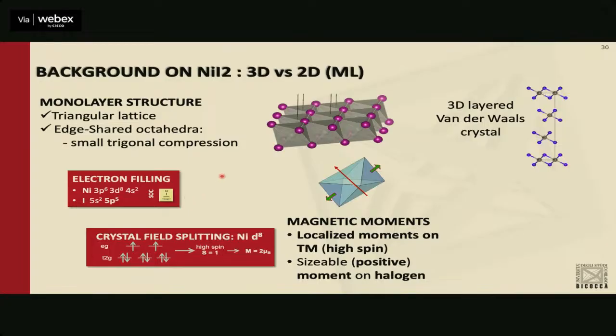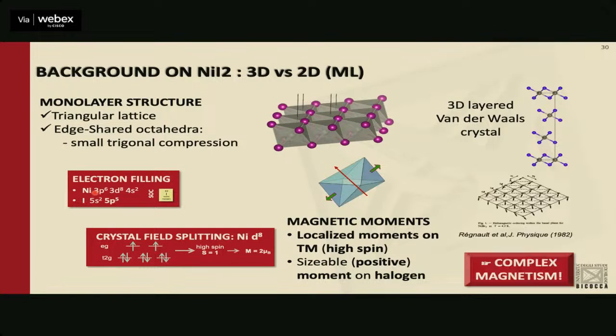We built a monolayer of nickel-I2. Nickel-I2 has nickel, which is an atom with a strong magnetic moment. And this material in the 3D limit was studied in the 80s in bulk form, and already it showed a complex spin texture. So now the question is, what happens in the monolayer limit?